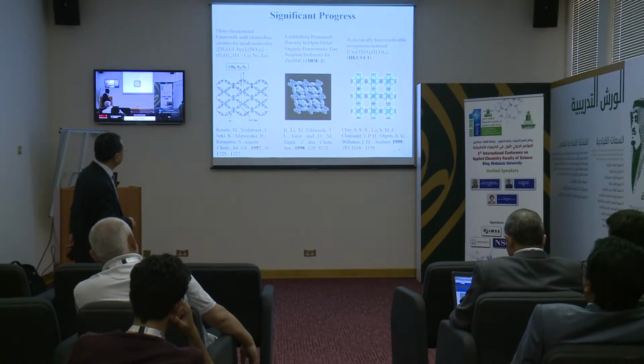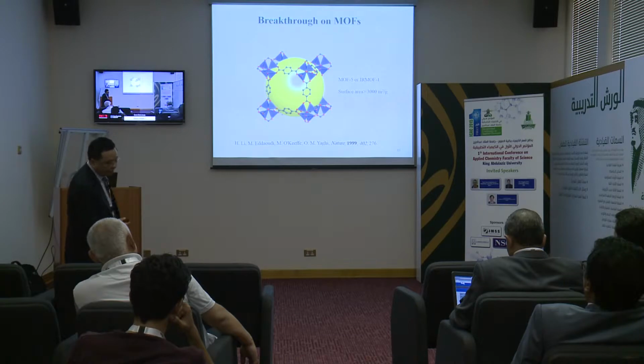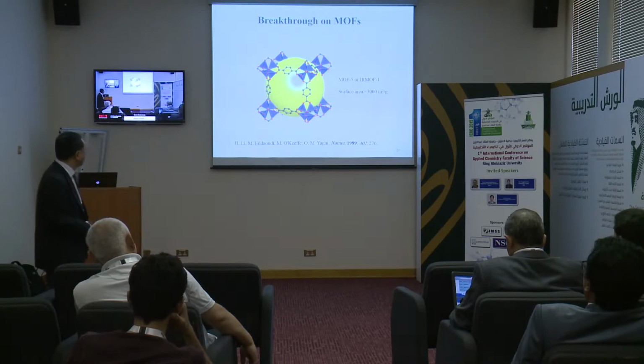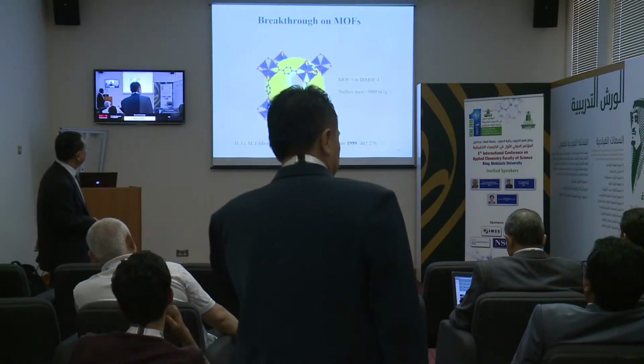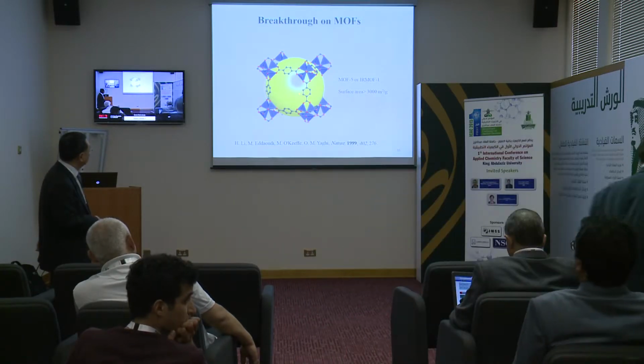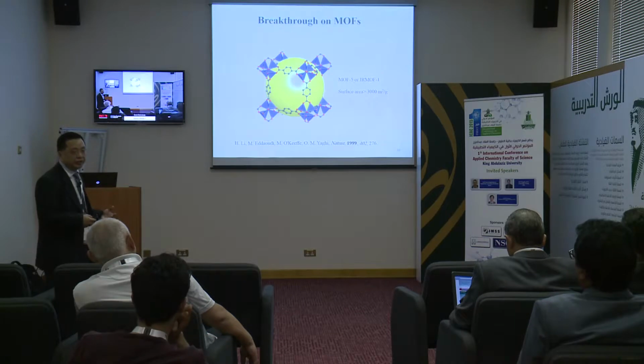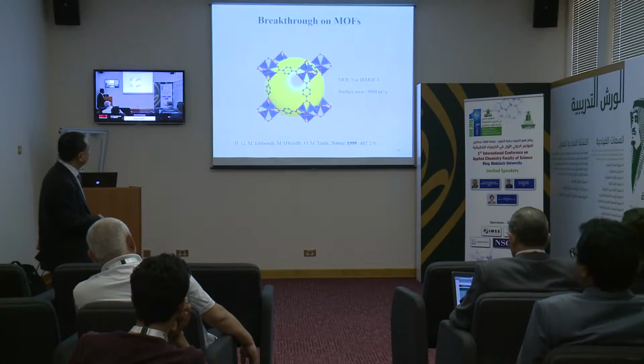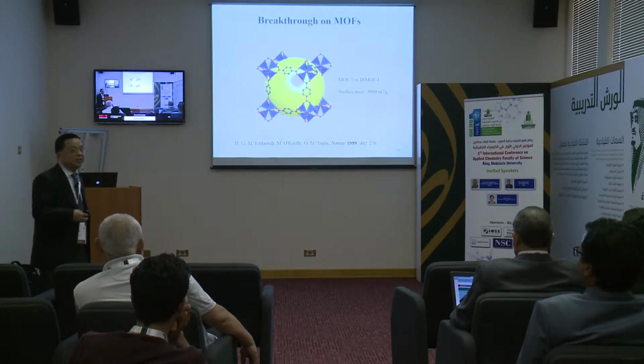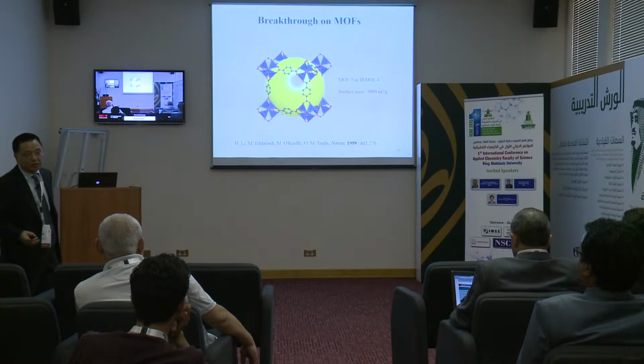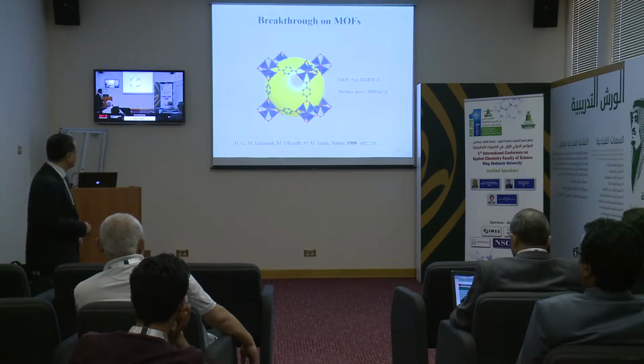This is another example. Of course, the most important contribution, the breakthrough in this field, is this one, MOF-5, the most famous. Apparently, this material can be easily synthesized from this organic linker, BDC, and zinc nitrate. And the high surface porosities immediately attracted massive attention. So this is certainly a breakthrough. Mohammed also established these high porosities.